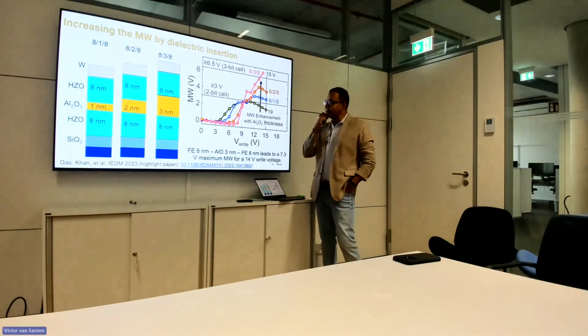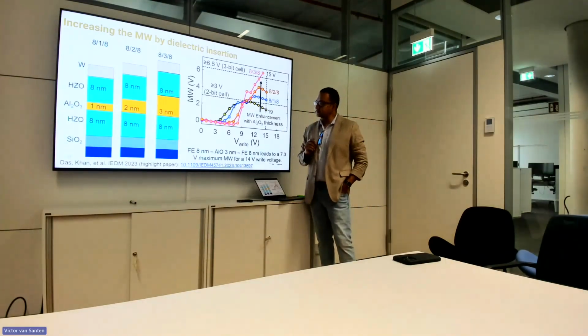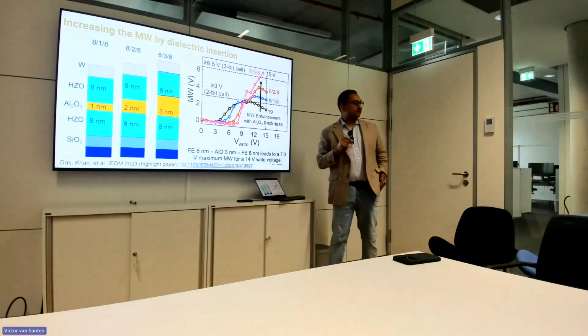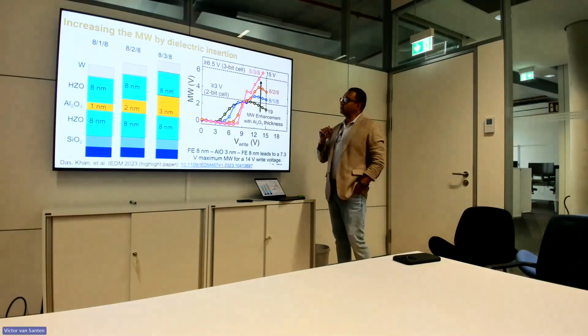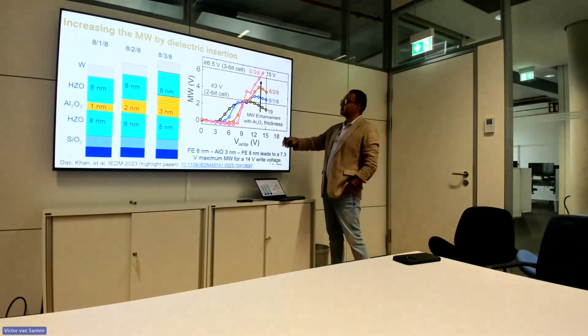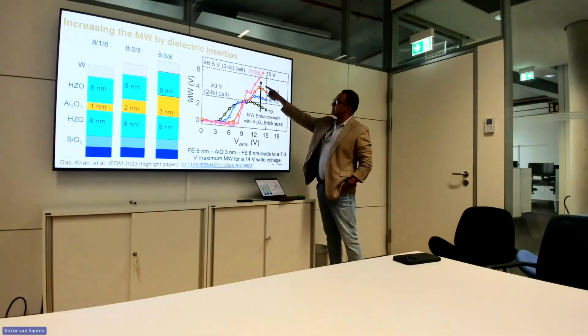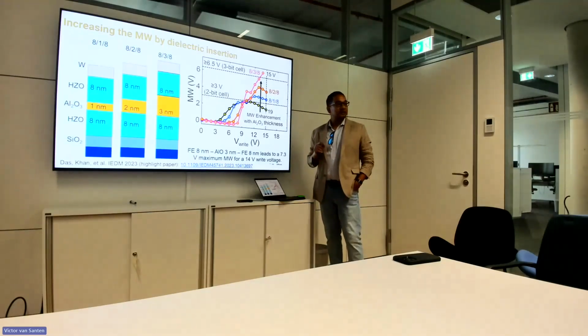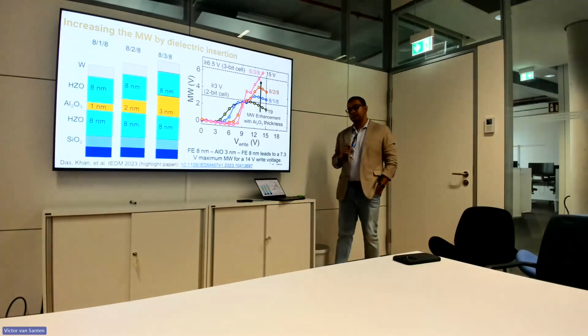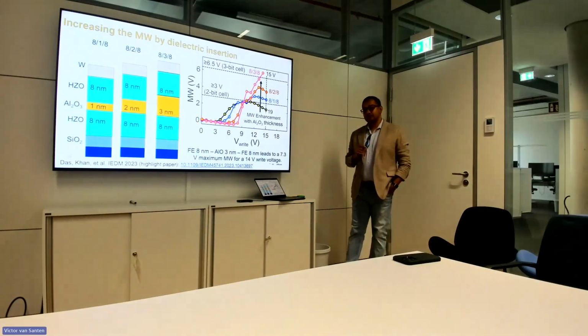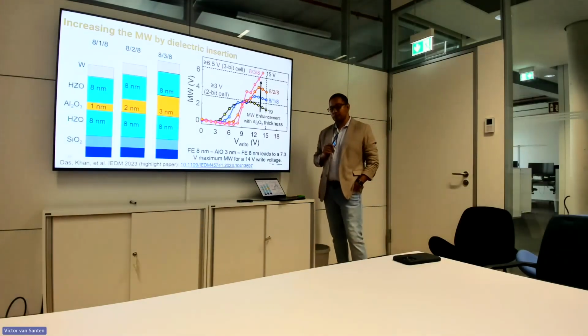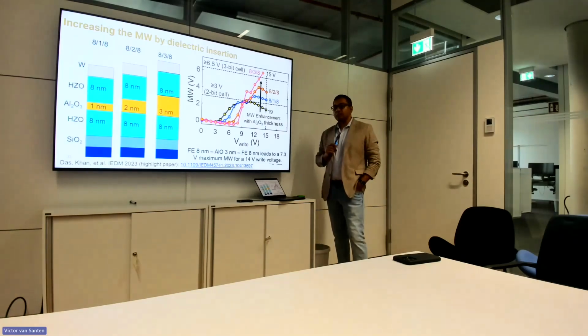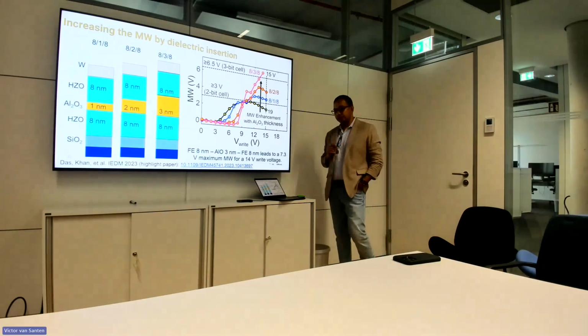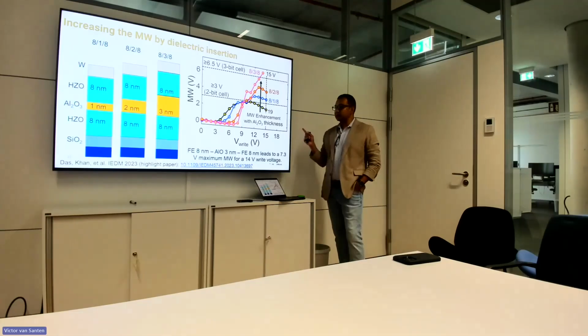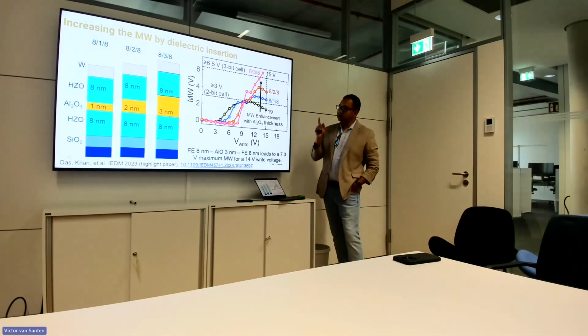Okay, so then my postdoc, Dipjyoti, increased the aluminum oxide layers. Now it looks very simple, but as we increase the aluminum oxide thickness, the maximum memory window goes up almost linearly. Just to make sure, you cycle the device and the window is stable. It's not an artifact or temporal effect from the traps. So you keep cycling and the window is stable. I'll show some of the results in the later slides, but the answer is yes and no.